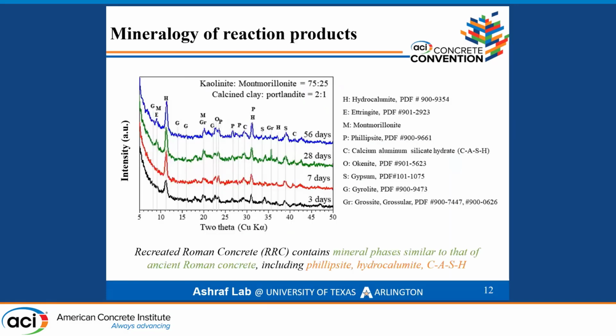In order to determine the mineralogy of the reaction products, XRD was used. Almost 80% of the reaction product was amorphous. Among the crystalline products, we have hydrocalumite. It is really prominent. Hydrocalumite formed by the reaction of alumina from the calcined clay, calcium from the Portlandite, and chloride from the seawater.